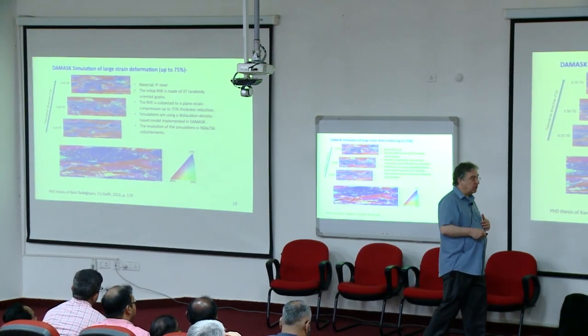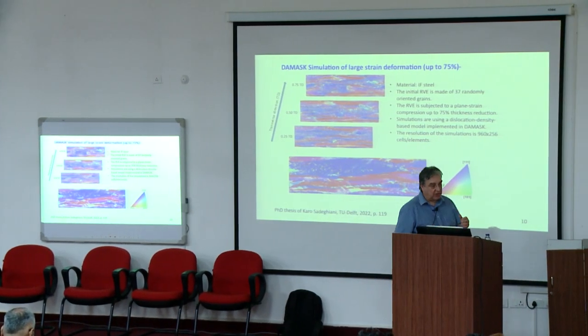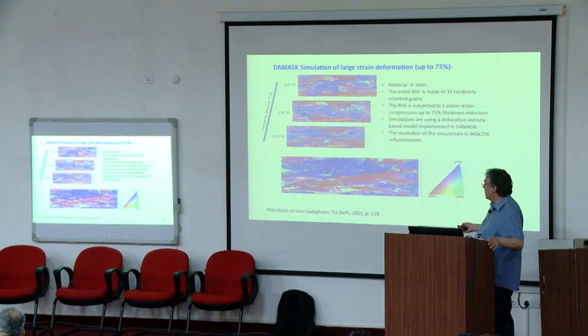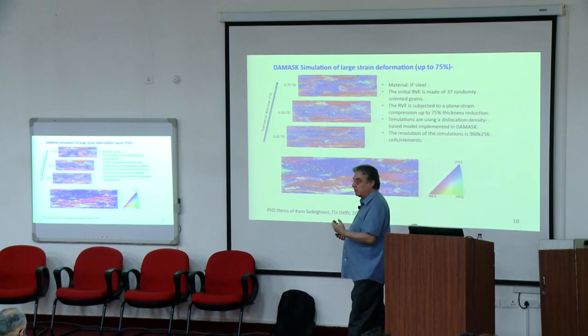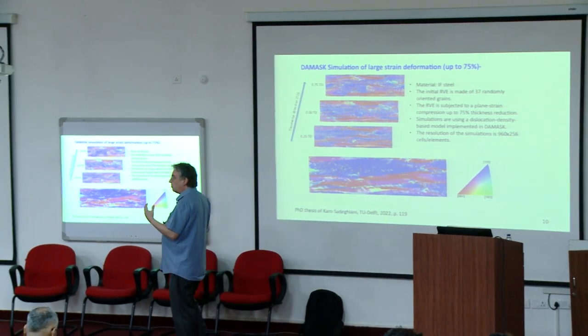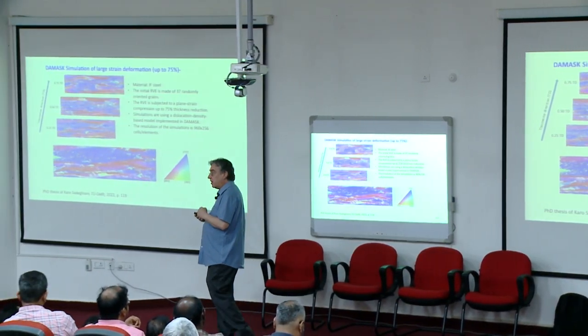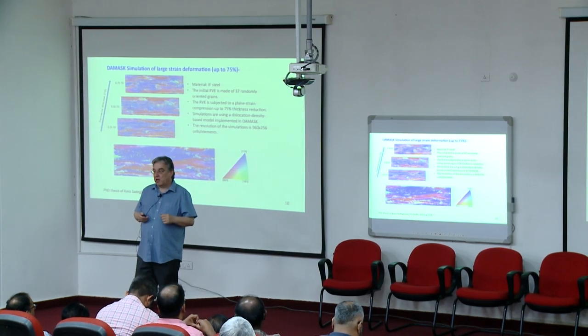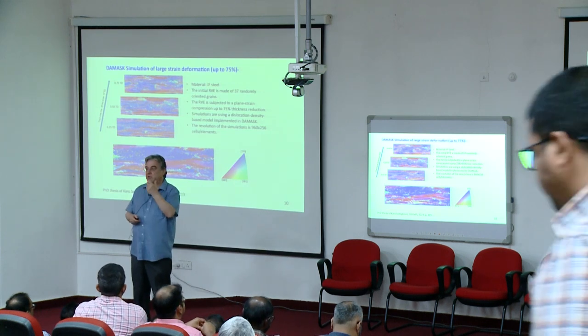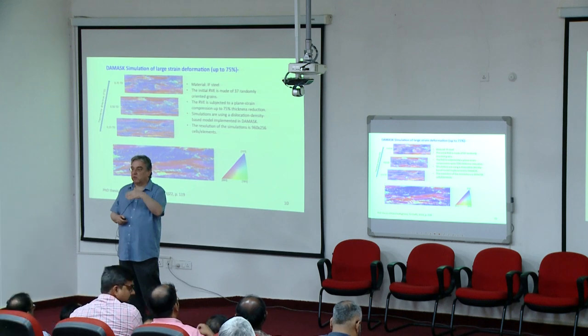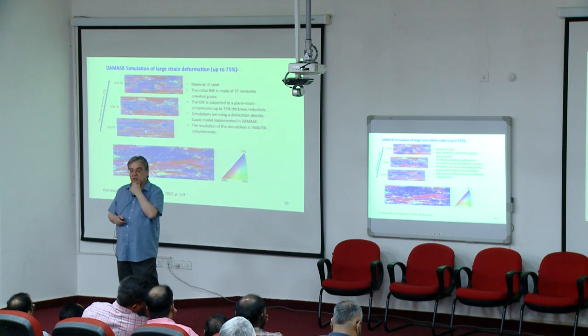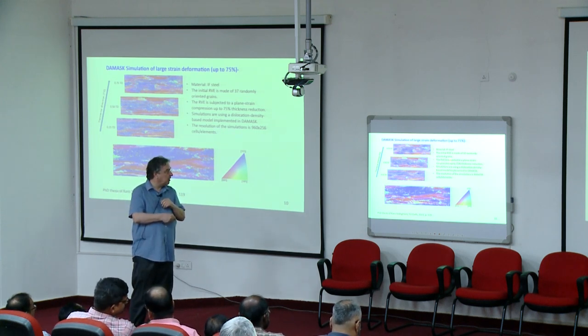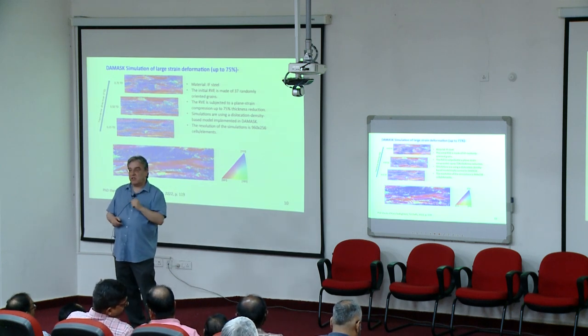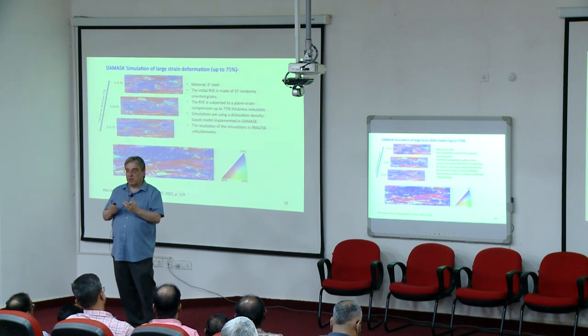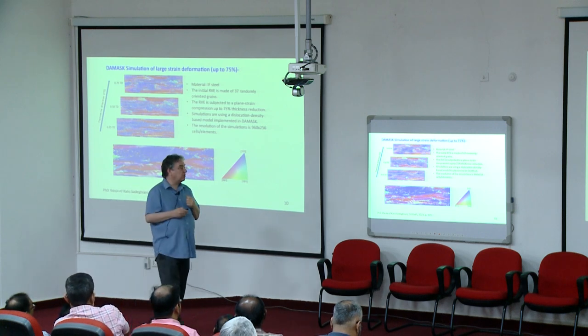This is very valuable to do this, but the problem is that just for making such a calculation, it costs about 3 weeks of CPU time. And this is just for one RVE. So again, this is very valuable from a scientific point of view, but for more applied interests, it's difficult. You're not going to compare, because probably the next day you want to know what, instead of 75%, what happens if I have 80% reduction or 85% reduction. Well, you have to calculate again for 3 weeks or for some weeks more. Because the other thing is that this was only for 37 grains. 37 grains is really very, very limited. You could argue whether 37 grains are really going to represent the microstructure or not.